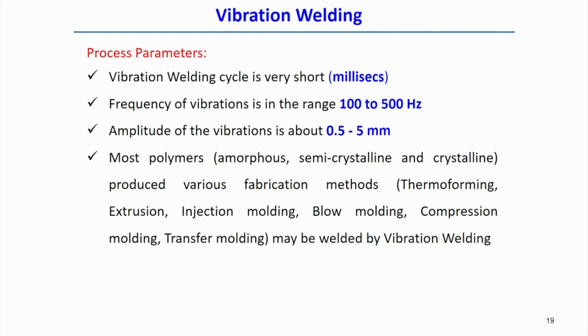So, in that sense the frequency levels are different in these two cases. And for the amplitude of the vibration, a wide variation is possible here, 0.5 to 5 millimeter. But in the case of the ultrasonic welding process, the amplitude of the vibration was very small, confined to only 0.05 millimeter, only 50 micrometer. Here we can range the amplitude of the vibration from 500 micrometer to 5000 micrometer. So, in that sense it is different from the ultrasonic welding process.